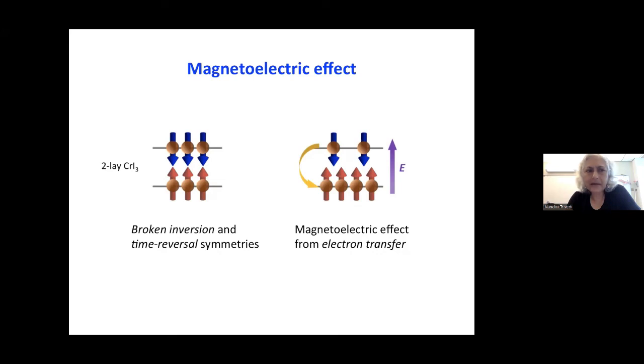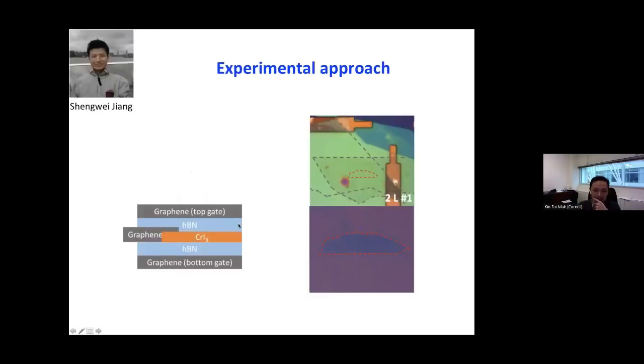Also, is there electron transfer in the plane? So does it become an in-plane conductor? I guess the question is whether one can do some transport in the system. Unfortunately, the band is very flat. It's a 3d band, and there's also quite a bit of defect density in the material. So the electrons can very easily localize. I think the Anderson mobility edge corresponds to a very high doping density. So in the doping density range we can study, it is basically like a piece of wood. It just doesn't really conduct electricity.